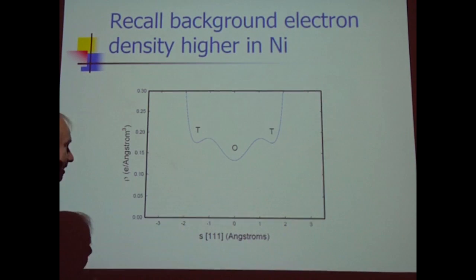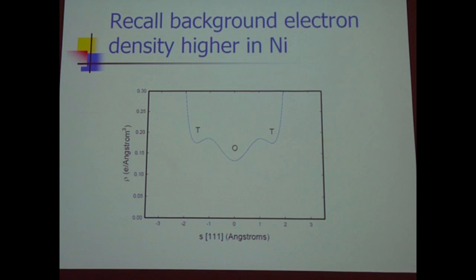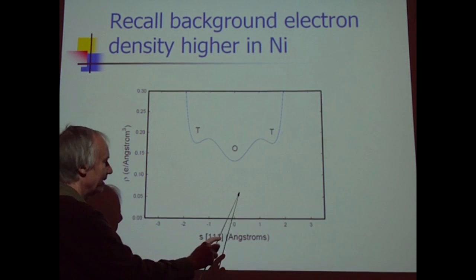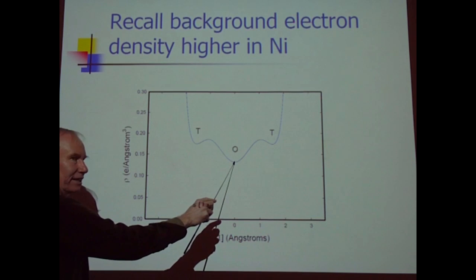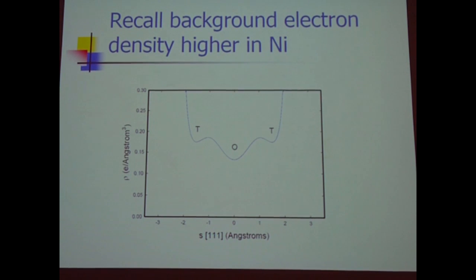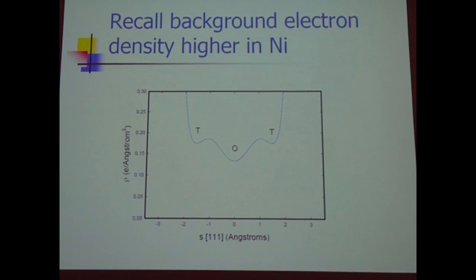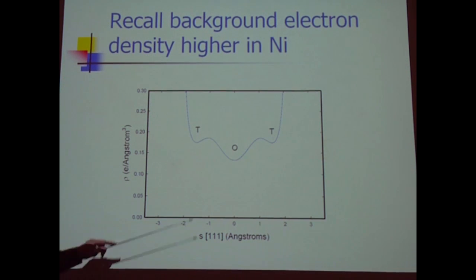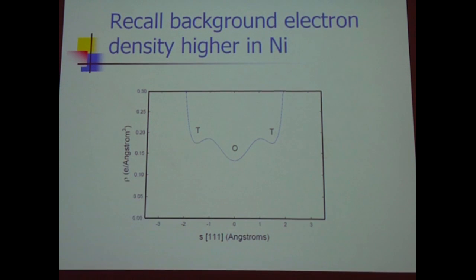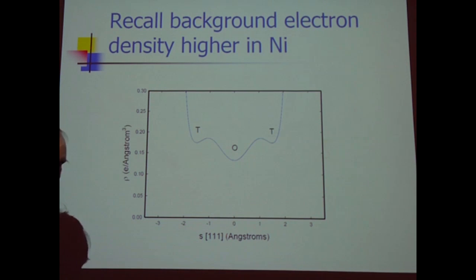Now, we recalled our arguments about background electron density, and the background electron density in the case of nickel is higher. So we recall that according to embedded atom theory, at least in one calculation, the hydrogen was looking for 0.069 electrons per cubic angstrom, which are down here. And what you get at the O site is up there. So you'd expect O site occupation, which is observed, but because there's so much energy difference here, we conclude that the solubility is going to be down.